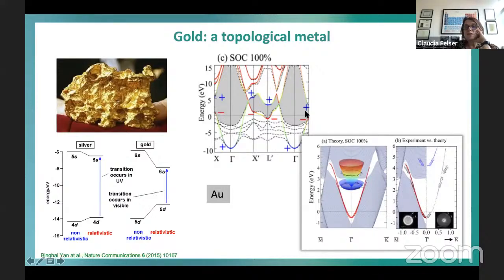If the Fermi energy were a little bit higher, it would even be a topological insulator. That the surface states really connect the valence and conduction bands was shown by two-photon photoemission spectroscopy, because above the Fermi energy these are unoccupied bands. So we could really show that gold is a topological metal.